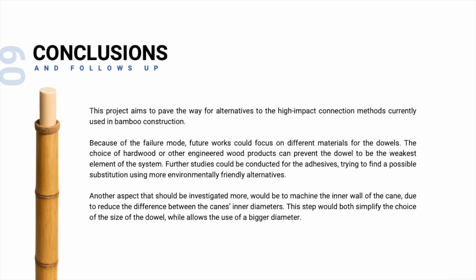So to conclude, this study shows that the current joint design is limited by the choice of the dowel material. And if we want stronger joints, we should consider alternatives such as hardwood dowels or even engineered wood products, which could provide higher strength and reduce the risk of premature failure. And at the same time, the adhesive deserves further attention. In fact, epoxy works well, but has a very high environmental impact. And exploring more sustainable resins or bio-based adhesives could be a valuable direction for the future.